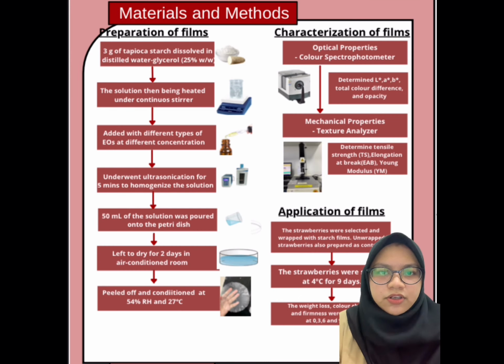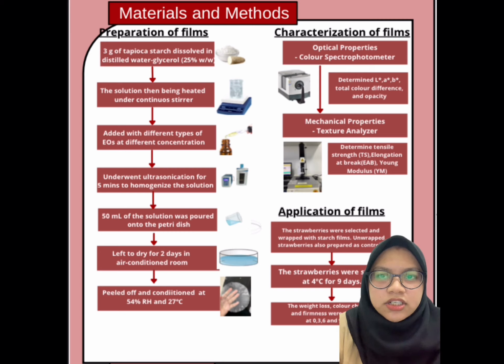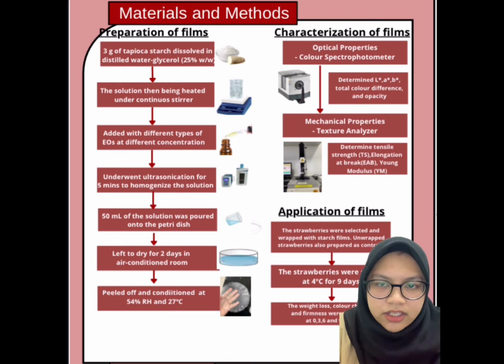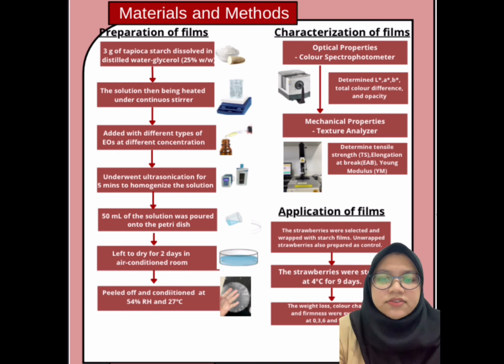For the preparation of the films, it begins with tapioca starch dissolved in a distilled water and glycerol solution, and then the mixture is heated under continuous stirring and the solution is added with EOs at different concentrations. Next, the solution underwent ultrasonication for 5 minutes to homogenize it. Then 50 ml of the solution was poured onto a petri dish and left to dry for 2 days in an air-conditioned room. After that, the films were peeled off and conditioned at 54% RH and 27 degrees Celsius.